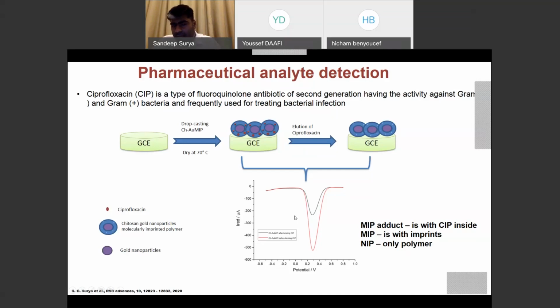The measurement that I have shown here corresponds to MIP adduct and MIP. The MIP adduct is shown in the form of red curve, and the black corresponds to the MIP after removing the CIP. This particular kind of measurement is called DPV, differential pulse voltammetry, where the reduction currents are read from the GCE electrode.